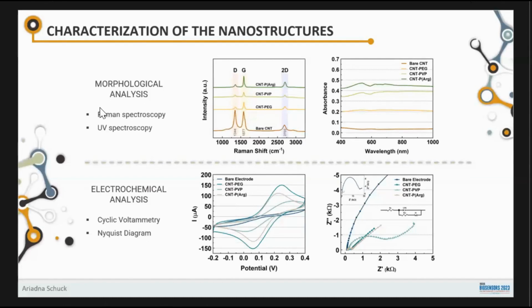And the most important part is the electrochemical analysis. I want to guarantee that I have the signal amplification for the measurement, because anyway, I'm dealing with 3 different biomarkers that have many different concentrations in the blood. And some of them need a high sensitivity to be detected. So I checked the amplification of the signal compared with the bare electrode here in the redox response for the CV measurement. And the CNT here has an increase in the peak that was better compared with the bare electrode here.